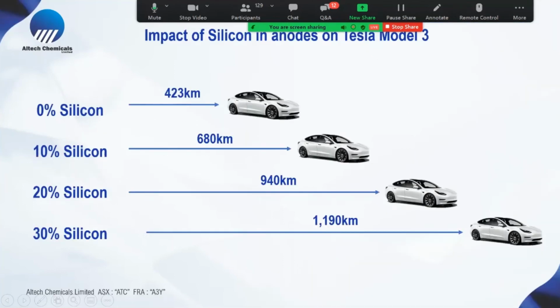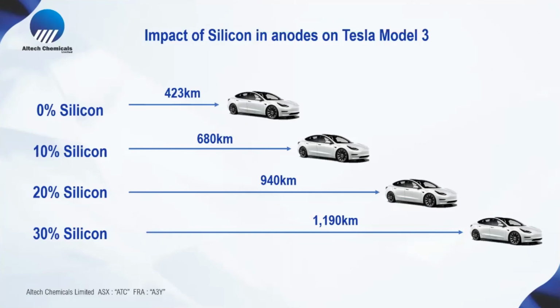Now, our technology, if you look back here, what is the impact of that to the retail market? If you have a Model 3 with 0 silicon, it travels about 423 kilometers on a single charge. Now, if you are able to add 10% silicon in that battery, you'll be able to travel 680 Ks on a single charge. 20% will get you 940 Ks, and 30% silicon will allow you to travel nearly 1,200 Ks on a single charge. Now, the EV manufacturers will still give you around 400, 500 kilometers because you're traveling around the city. And what it will allow them is to downsize the size of the battery and the weight of the cars. So we're very focused on Europe.